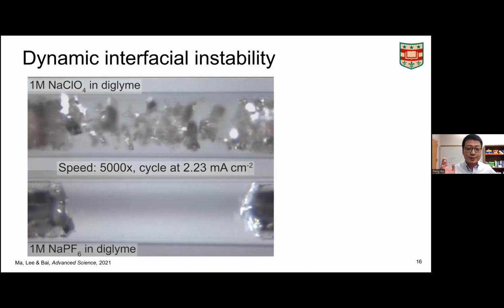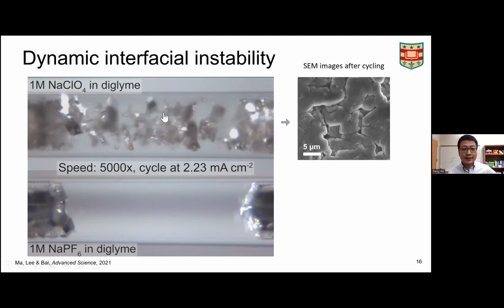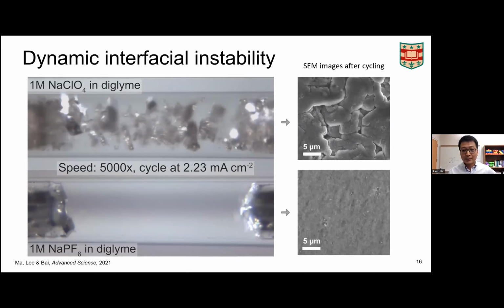And if you put this into a real battery and do the test, eventually we'll see that for this kind of structure within the actual battery, you will see so many voids, which you don't want to have, because that's the sign of compromised, deteriorated performance. But for the good electrolyte, you always have a very smooth, almost defect-free deposition surface or plating surface. So the other one is not so good, but we have a very nice choice, right?